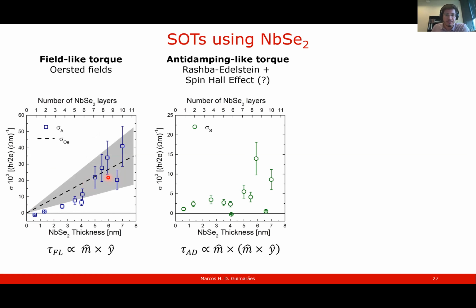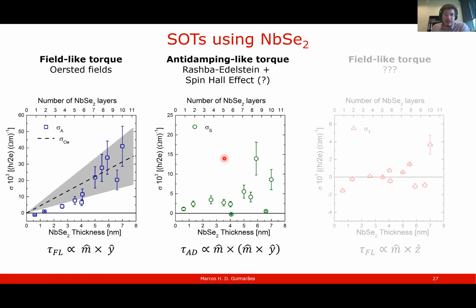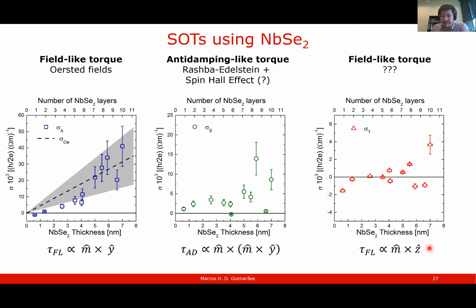the ferromagnet. Now, if you look at the spin Hall-like torque, M cross Y torque, look at the intensity as a function of niobium diselenide thickness, it looks more or less constant there for lower thickness, and maybe it increases a little bit at the higher thickness, indicating that we have the presence of both an interfacial torque and some bulk effect. So it would be kind of a Rashba-Edelstein plus a spin Hall effect. But now this weird torque, the M cross Z torque, which is not allowed by symmetry, is basically all over the place as a function of thickness. So this got us thinking.